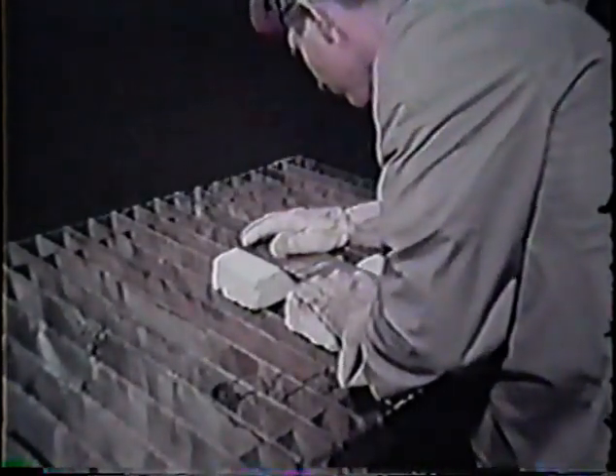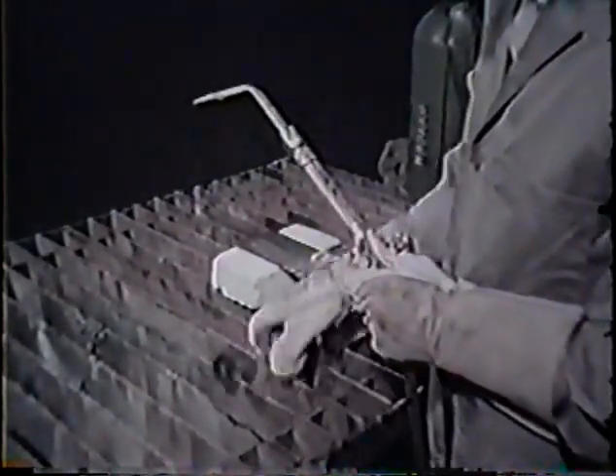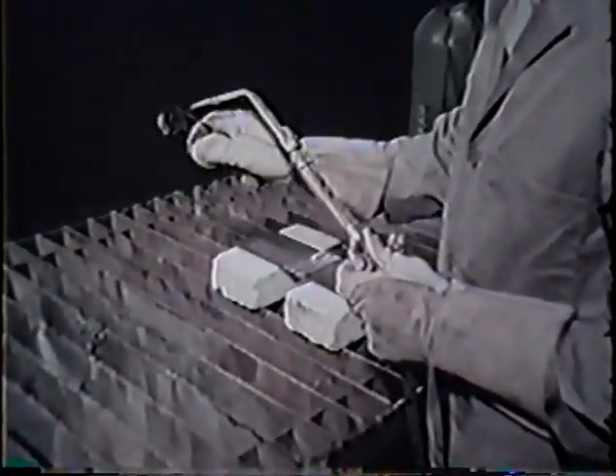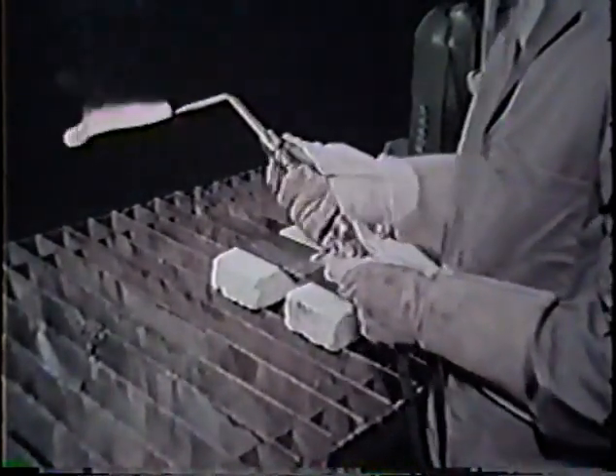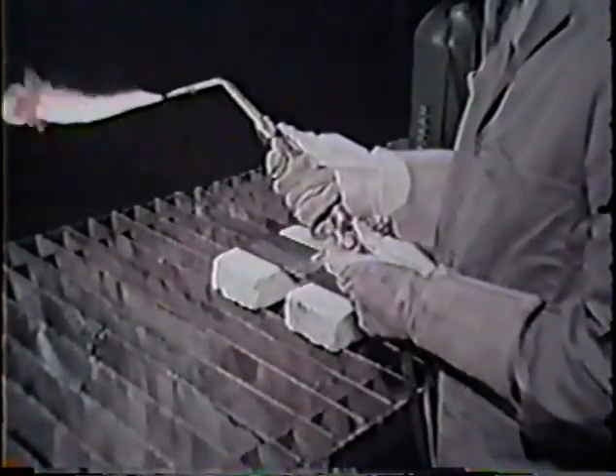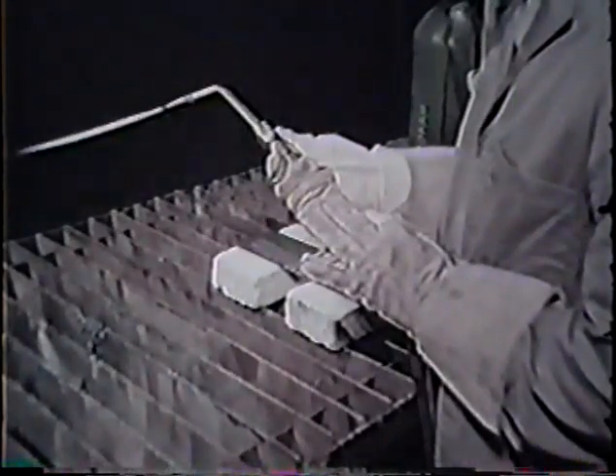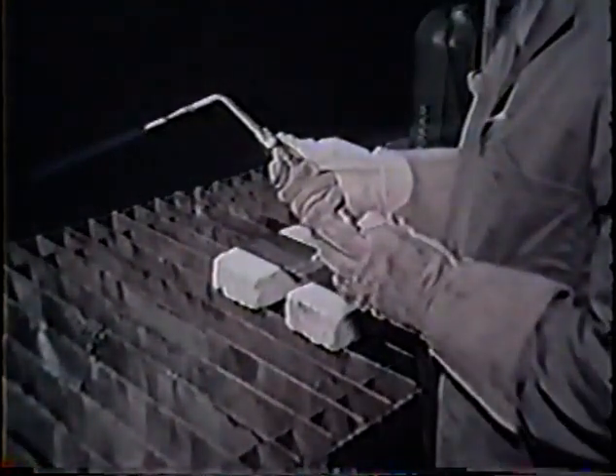Now that the metal plates are properly spaced, light off the torch and select the proper flame. To do this, just barely crack the fuel valve, then ignite the torch with a striker. Adjust the oxygen and gas in successive steps until a slightly oxidizing flame is produced. The slightly oxidizing flame is used for most welding with MAP gas. The inner cone is long and pointed and is surrounded by a dark blue outer flame.